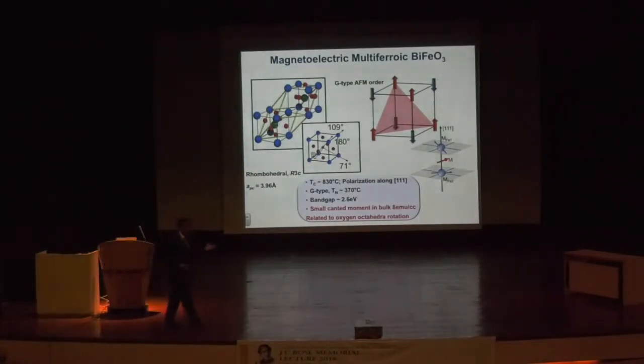I told you a few minutes ago that this has super exchange interactions between the iron. That's shown here. It's got this G-type antiferromagnet. In very simple terms, you have 111 planes of the perovskite structure, which are antiferromagnetically coupled to each other. Now, if that's all that happened, this would be a little bit boring material. Actually, it would not be useful at all for us.